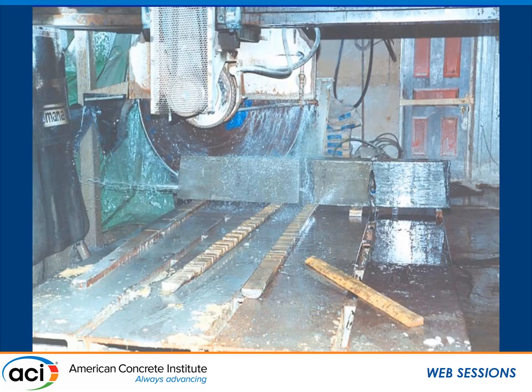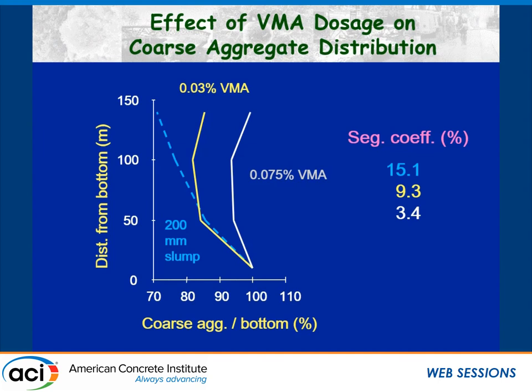If we were to cast those columns or wall elements and then saw cut them, polish them, and look at the coarse aggregate distribution using image analysis, this is what you would find. So all of these values here are the coarse aggregate content divided by the coarse aggregate content at the bottom. So everything is normalized to what happens at the bottom. And just as a reference, you have the blue one, which is a vibrated concrete. So this is 8-inch slump, 1.5 meter wall element that is vibrated into lifts. And this is the distribution that you get.